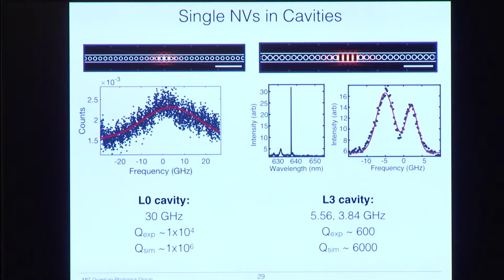Unfortunately, this L3 cavity has low intrinsic Q, so even in simulations, we could only get Qs around 6,000. Not that I tried particularly hard, but it's definitely lower Q than the L0 cavity. And in fabrication, we get Qs of around 600. So while we can get more decent line widths, the quality of the cavity itself is worse.